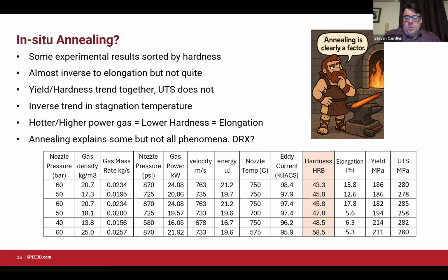So these are somewhat similar effects to if we were to take the part out after spraying it at low pressure and then heat treating the part. So we're definitely seeing more than one effect here. We're not just seeing an in situ heat treatment as a result of the additional power in the gas as a result of the higher pressure. But I think the hardness is definitely telling us that we're seeing some annealing in process.